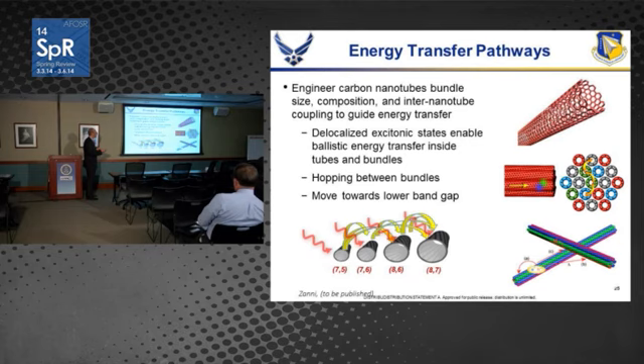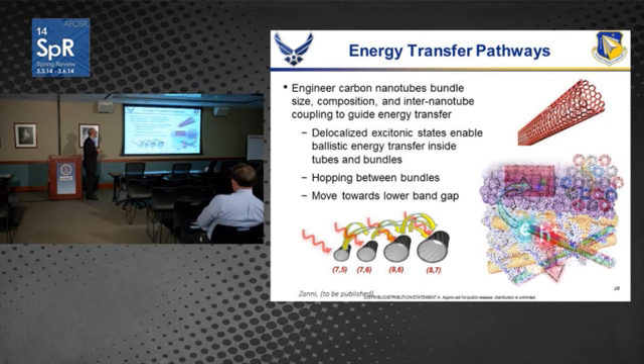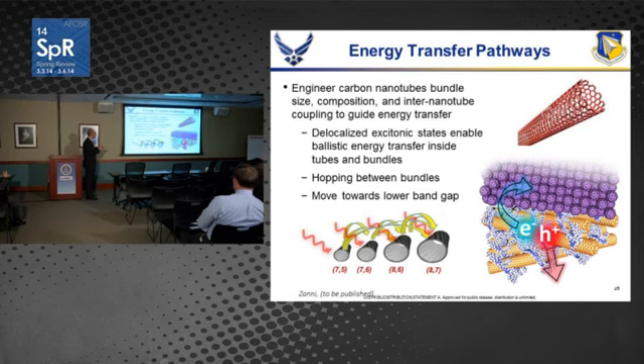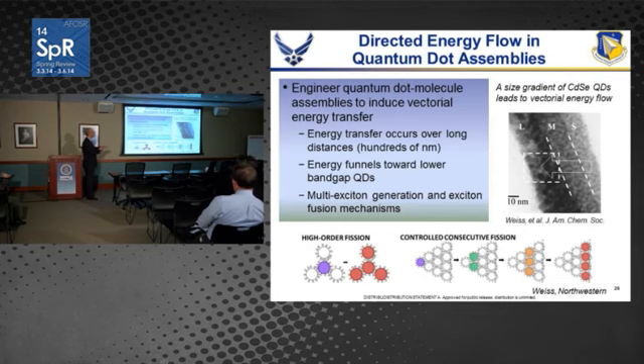We can also try to use nanostructures to control the energy transfer. Martin Zanni and Mike Arnold at Wisconsin are using nanotubes where you can get ballistic energy transfer through the nanotubes, to get very fast and efficient transfer and guide energy flow from nanotubes with higher band gaps to lower band gaps, so we control this energy flow. Emily Weiss has also demonstrated that you can do vectorial energy transfer, controlling the flow by going to smaller band gaps in quantum dots. Have small quantum dots, medium size, and larger ones that direct the flow of energy. You can funnel energy flow.